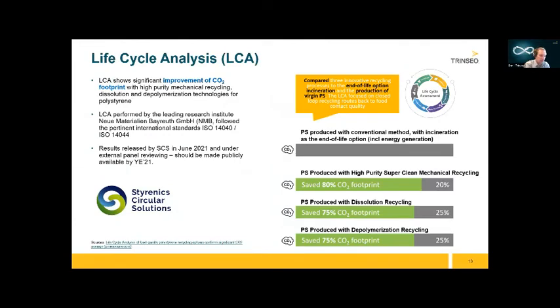Not only is there circularity achieved within the styrenics, we also started to generate some environmental data within the Styrenic circular solution. And as you can see, from an environmental point of view, it's no surprise that the mechanical recycling has the greatest benefit in terms of CO2 savings. In fact, the super clean mechanical recycling reduces the CO2 footprint versus a virgin polystyrene by 80%. The dissolution and depolymerization also have a great benefit when it comes to CO2 savings.